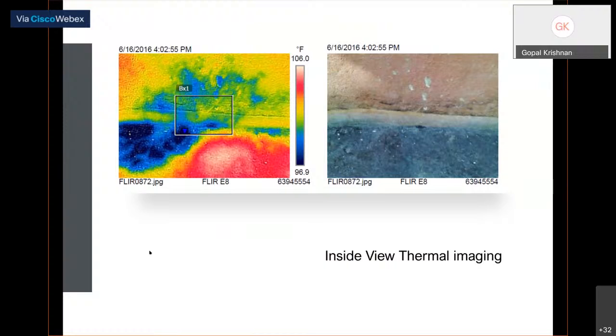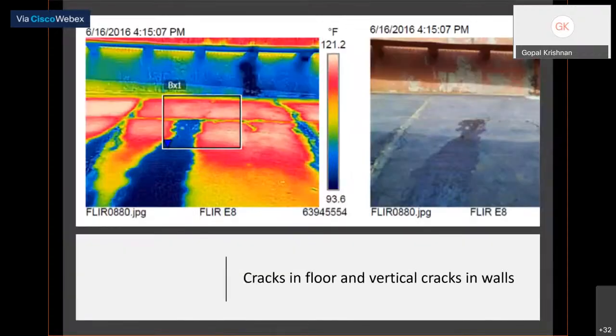So we can identify the weak spots creating the source of the leakage, high porosity, and where even a minor crack allows the water to seep through. Only thermal imaging can help us identify those areas.